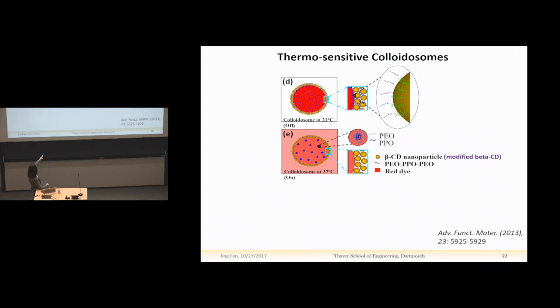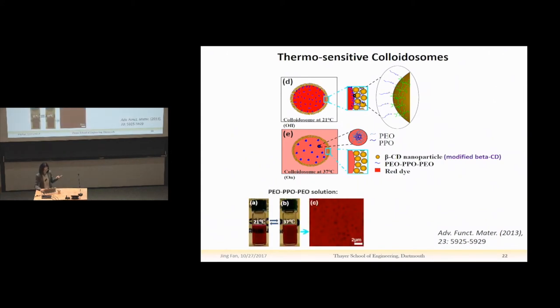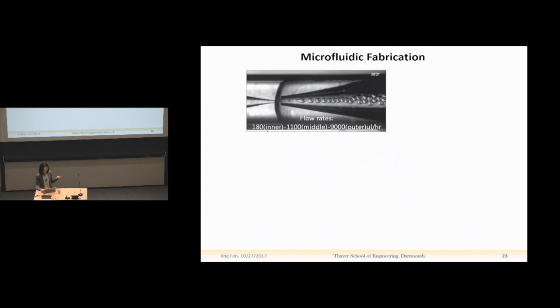And at elevated temperature, at 37 degrees Celsius, these block copolymers will detach from the nanoparticle surface, and they also aggregate to form micelles. So this will open the pores and switch on the release. So this allows us to switch the release from this system on and off. And we characterize the nanoparticles by TEM. And this is what we made.